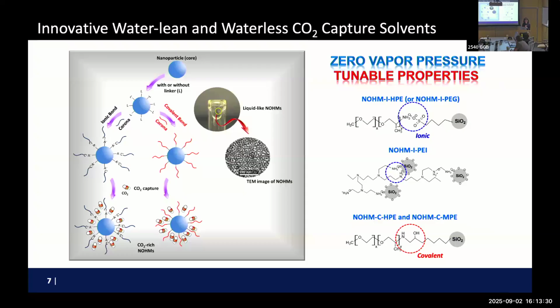And the reason I really like this design for carbon capture was I really wanted to increase as much free volume as possible. So the tethering of this polymer onto nanoparticles was done with the right grafting density, right size, right conformations to maximize the free volume between polymer chains so that I can jam-pack as much CO2 as possible. And I was hoping that this will behave similarly to an ionic liquid, which has almost zero vapor pressure. So you can increase the temperature to 100 degrees C. Hopefully there's no fume coming out, which is one of the ways you lose a lot of your liquid solvents.